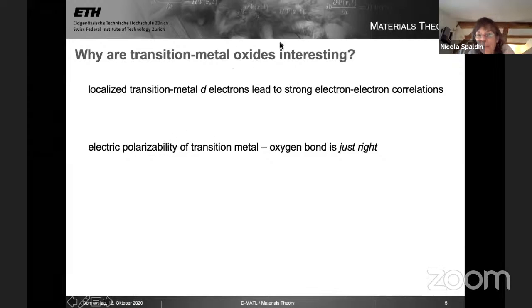The other part of a transition metal oxide is, of course, the oxygen, and this also is important in making the physics of transition metal oxides really special. And here it's really the electric polarizability of the chemical bond that forms between the transition metal and the oxygen, which is just right in its response to perturbations like electric fields and, for example, changing the bond distance. It's a very polarizable bond.